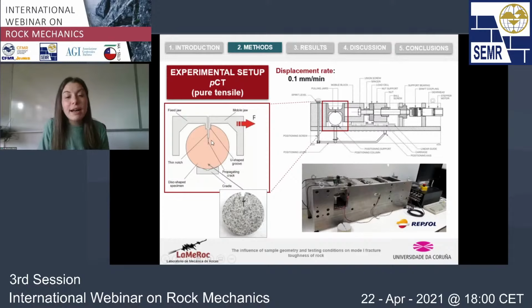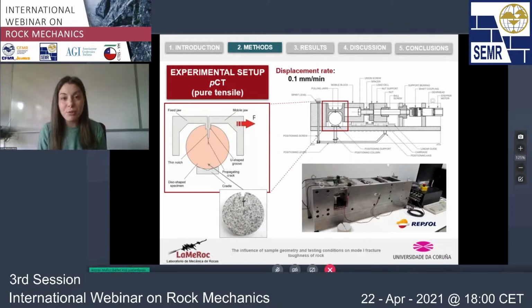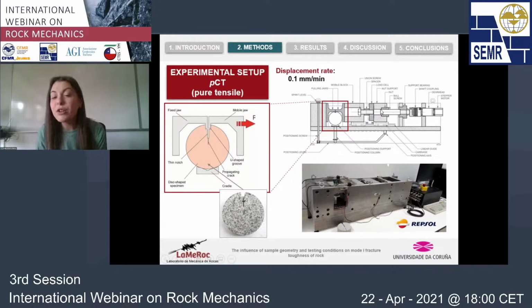So we have a tensile stress here that appears at the level of the notch tip, and the fracture propagates here along the ligament plane vertically. So we have used the same displacement rate in these experiments as in the case of the SCV to avoid any discrepancy in this regard. And the movement of this jaw here, we can see it in this picture. The movement of this jaw is accomplished by a ball screw that converts the rotatory motion of a motor into linear displacement. And this is a very simple configuration, and we can have a very high accuracy on displacement.